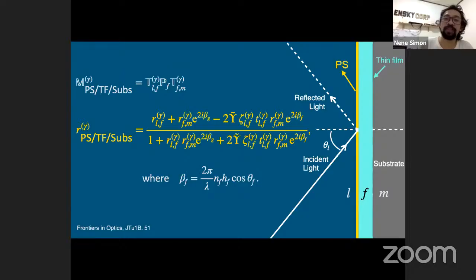With the transfer matrix method, we can derive expressions for the reflection coefficient for a perfect sheet, thin film, substrate system. The effective transfer matrix is given by this equation. M is equal to T_LF times P_F times T_FM. And through the scattering matrix approach, the reflection coefficient R is given by this expression. Notice that this resembles the reflection coefficient for a thin film. So if there is no perfect sheet, one can simply zero out the epsilon tilde terms, this term and this term.